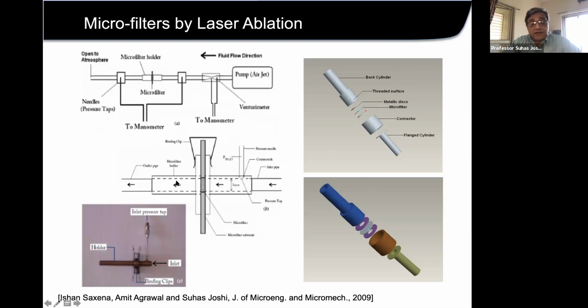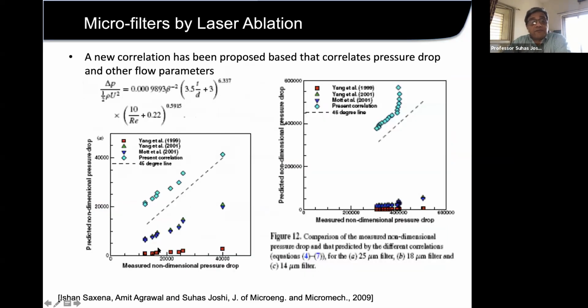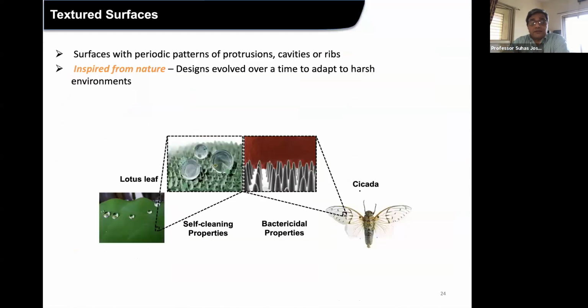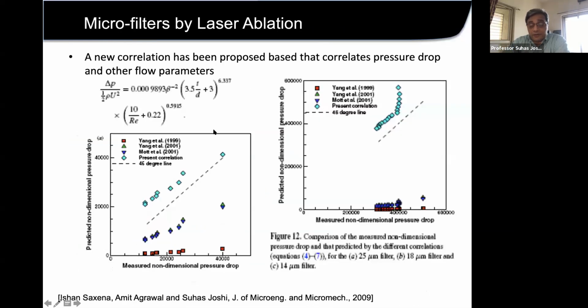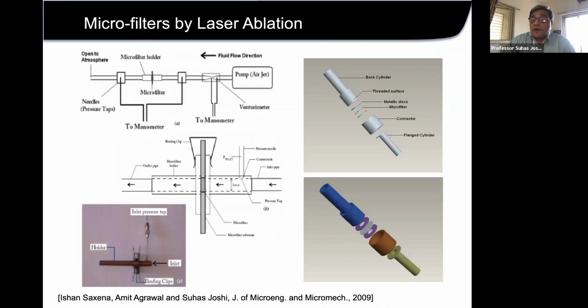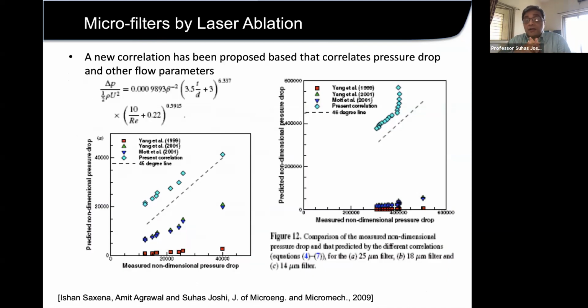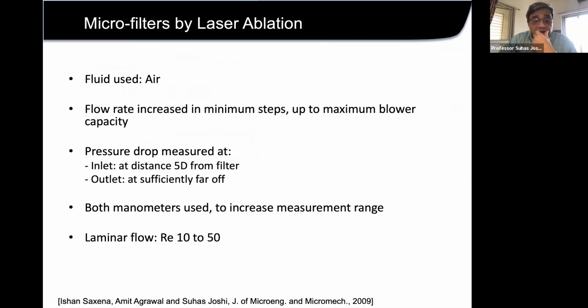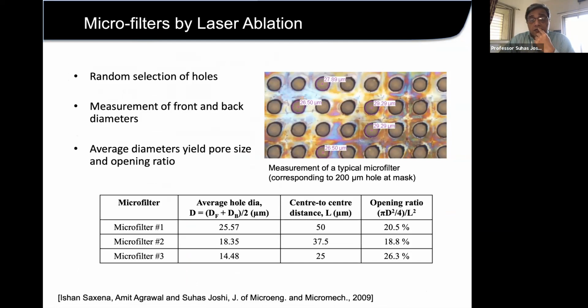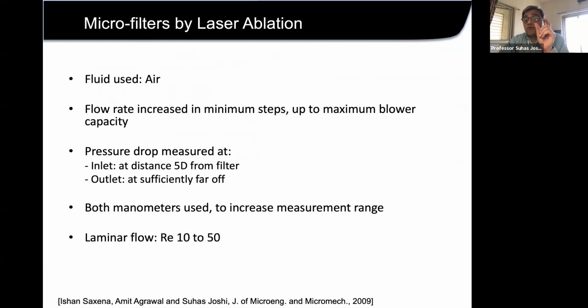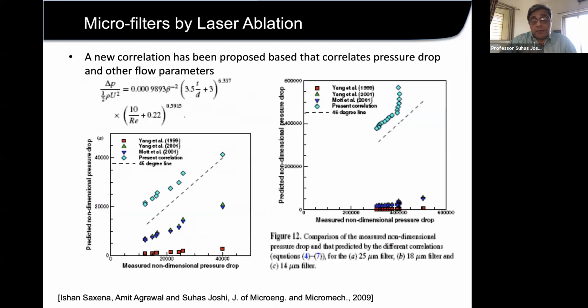One of my colleagues, Amit Agrawal, was involved from that point of view in this particular work. We measured the pressure drop across the microfilters, and we could get fairly reasonable results at that point. We could get some kind of reasonable estimate of the pressure drop across such filters. I'm not able to get the number, but I think 16,000 holes were made in a 3 to 4 mm size. We made about 16,000 holes in that small size using the lasers. Of course, it was a polymeric plate.